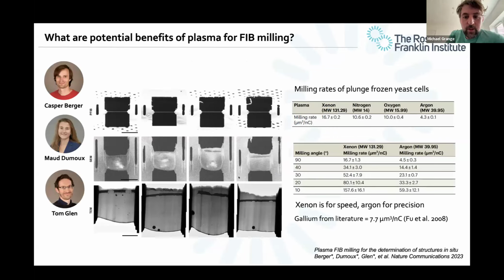And as part of that, what we wanted to understand is the different trade-offs with the milling rate. So here's some very nice lamella, but what we also did was to try and measure how much material will move as a function of time and as a function of current. And also at different angles. And what we found is that xenon is the fastest for milling material. So you can see here, it's about twice as fast as the published values for gallium in water. And it's faster in nitrogen oxygen, but quite a bit, so about 4 times faster than argon. So argon is actually slower per unit charge than gallium, which was an interesting observation.